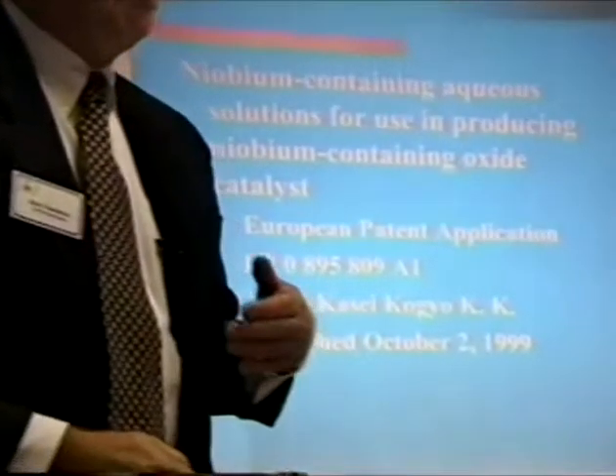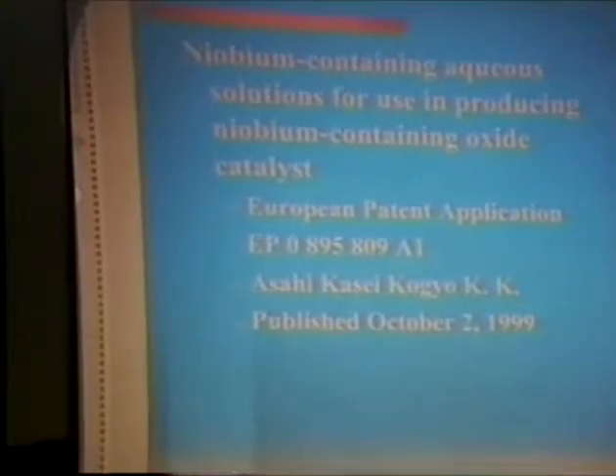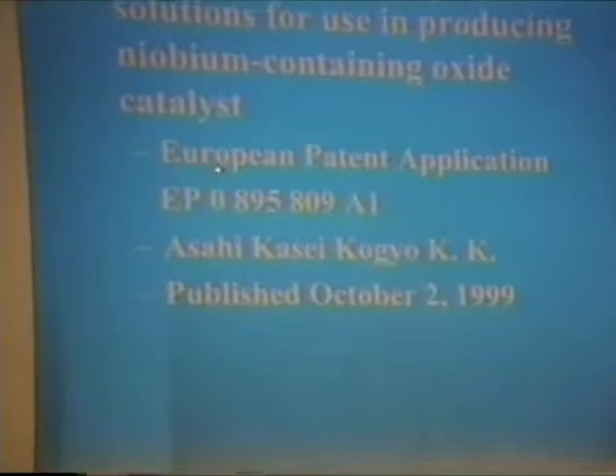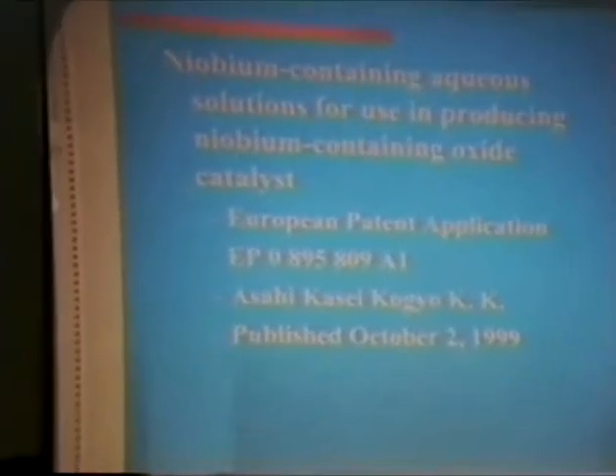There was some work that addressed some of these issues of hydrolysis and polymerization and precipitation, and I can give you these references later. This was from some work from Asahi, one of the Asahi companies. In a European patent application, they demonstrated four different approaches for enhancing the performance of a molybdenum, vanadium, niobium, tellurium selective oxidation catalyst, and you did it by basically filtering out any suspended niobium compounds.